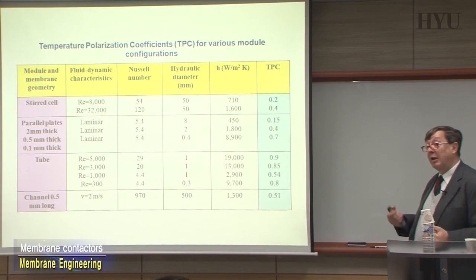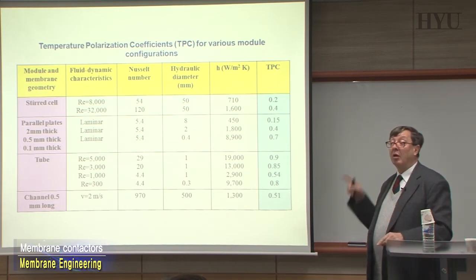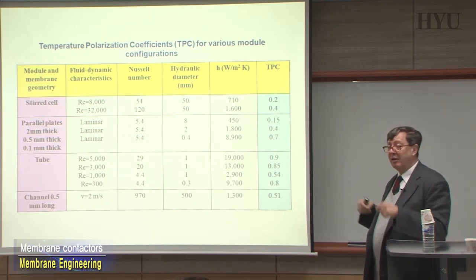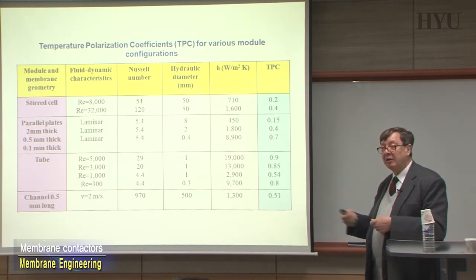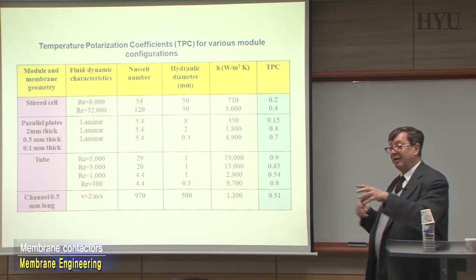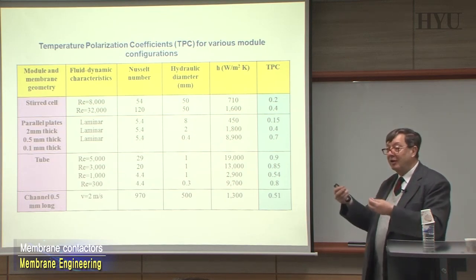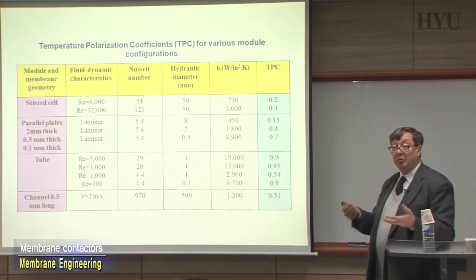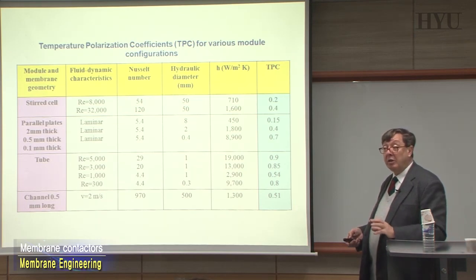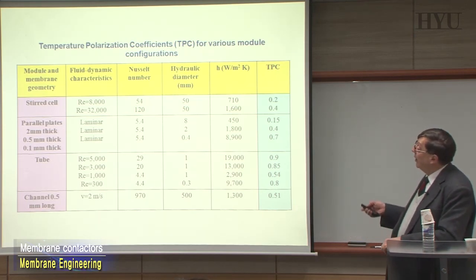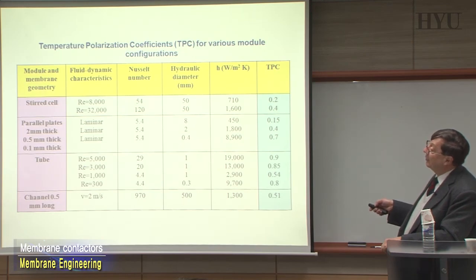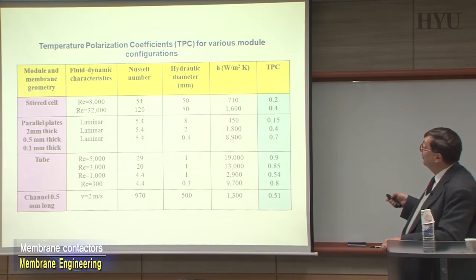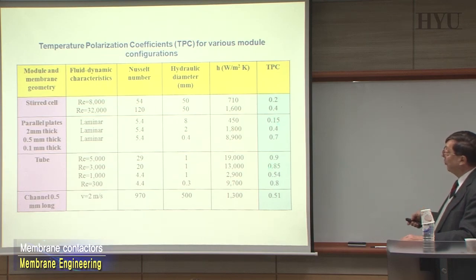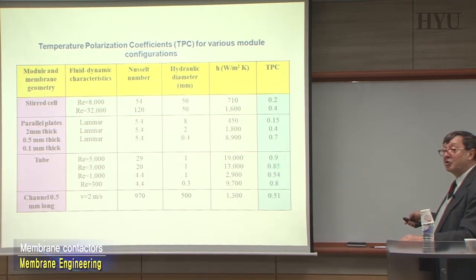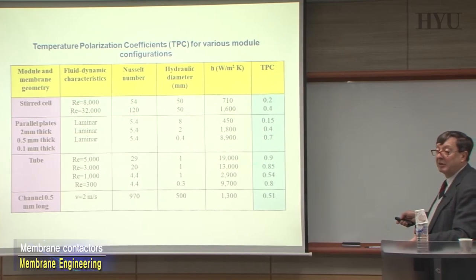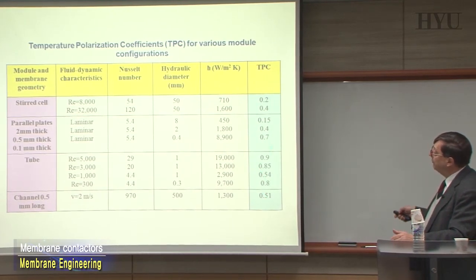Our PhD students today in Italy are mainly working on better understanding, better developing, better measuring, with a cell with 16 electrodes all around to measure the temperature profile that you create across the membranes. It's not easy, but that's what has to be done. In fact, here you can have the evidence of the temperature polarization coefficient. You can see here 0.2, 0.4. In some cases, you are approaching the good one, which is the ideal case. But normally, we are pretty far.